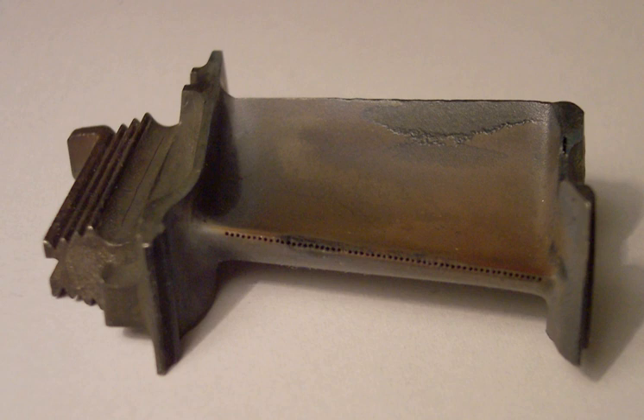Alumina-forming austenitic stainless steels feature a single-phase matrix of austenite iron FCC with an alumina oxide at the surface of the steel. Alumina is more thermodynamically stable in oxygen than chromia. More commonly, however, precipitate phases are introduced to increase strength and creep resistance. In alumina-forming steels, Ni-Al precipitates are introduced to act as Al reservoirs to maintain the protective alumina layer. In addition, Nb and Cr additions help form and stabilize alumina by increasing precipitate volume fractions of Ni-Al.